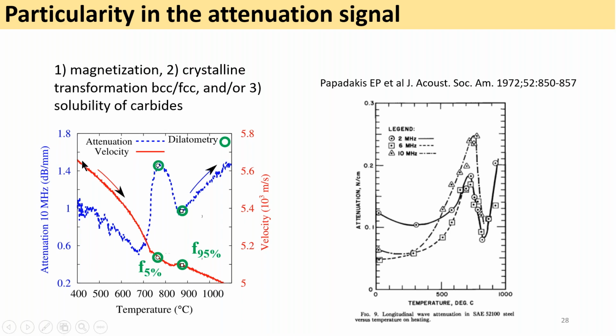But before moving to the austenite decomposition, I wanted to show that there is another parameter, the attenuation, that can probably give us a sign of the austenite formation. As you can see here, the blue signal, the attenuation, varies very importantly during the austenite formation. I've shown you here a very old paper from 1972, which showed this type of behavior, in which the magnetic transition is often accompanied by a rise in the attenuation. Then, as the austenite formation occurs, the austenite is non-magnetic, so the attenuation decreases again. This rise of attenuation corresponds to the increase in the grain size of austenite.